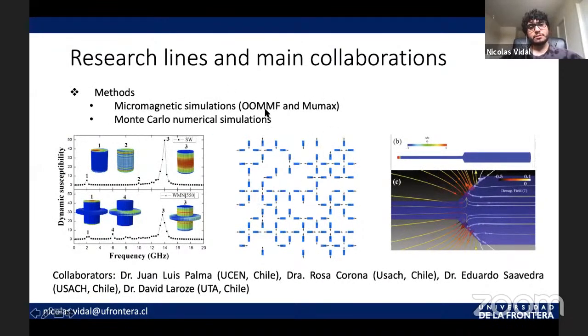Regarding the micromagnetic simulations, we use basically OOMMF and MuMax to perform them. For instance, here we computed the dynamical response, specifically the dynamic susceptibility, of a nanowire with a modulated diameter. We found that by including this modulation, we can see the appearance of different resonance peaks. Also, we have studied the current-driven domain wall motion in a similar nanostructure like this one.